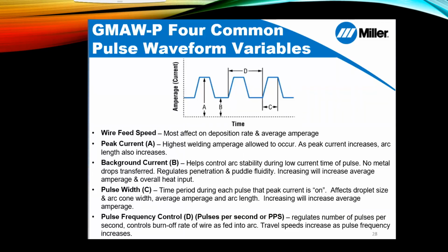Diving a little deeper into a pulse waveform, I like to look at this because it shows what is happening in the background. When we are pulsing, we're going between a low current or amperage, and then we're ramping up to a peak. At our peak, this is when we're going to transfer a droplet. Then we'll ramp back to our background, and that background is going to help keep our arc lit. It's going to help keep our puddle fluid, and then the process will cycle through. It'll keep happening. Sometimes you can be down to 27 pulses per second, depending on where you're at with wire feed speed. Sometimes when you're on the higher end, you might be up at 200 to 250 pulses per second. So that pulse per second, that frequency, the amount of droplets that we're transferring, will vary with wire feed speed.